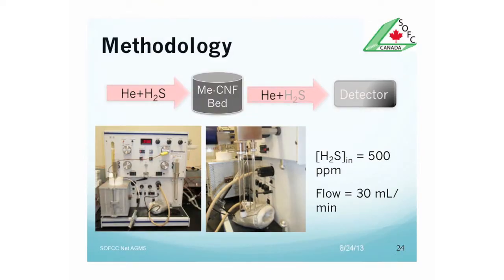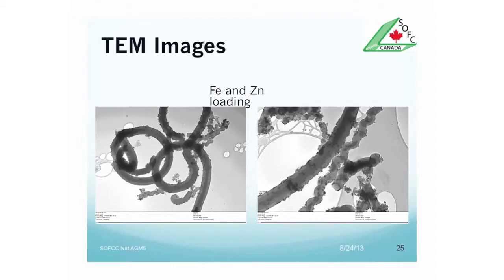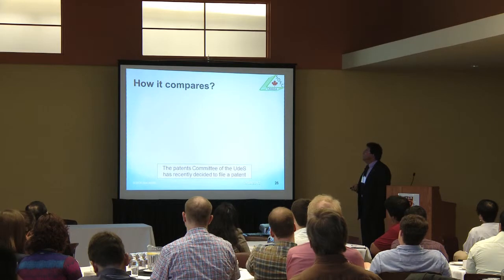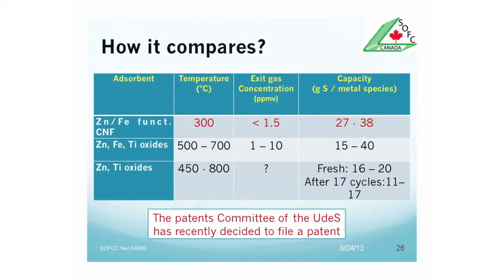Methodology is shown here. This is the equipment we use. It's a commercial one. We're starting with hydrogen sulfide at 500 ppm and a flow of 30 milliliters per minute. These are typical transmission electron microscopy pictures for iron and zinc loaded carbon nanofilaments. And I have no time to show you all the results, but I will show you how it compares with commercial systems. We have found these results in the literature, and actually we have ordered some of these commercial systems to do the same thing in-house.